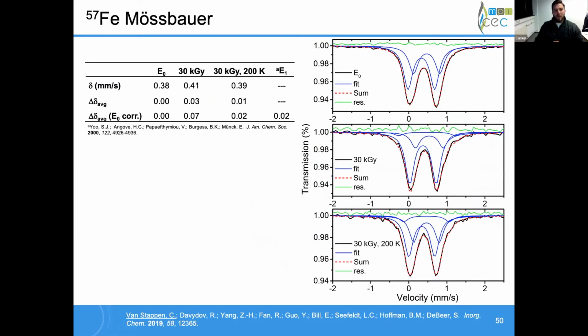Now, we took a step back and said, does this work out with the Mössbauer? And so we gave Eckhard Münck a call, and he actually still had one of the original samples from this 2000 study. And these are really tricky to get because they've been selectively enriched only at the FeMoco center, and the experimental side of making those is an absolute nightmare. But we took that sample and we cryo-reduced it, and we have a similar shift to what they observed before.